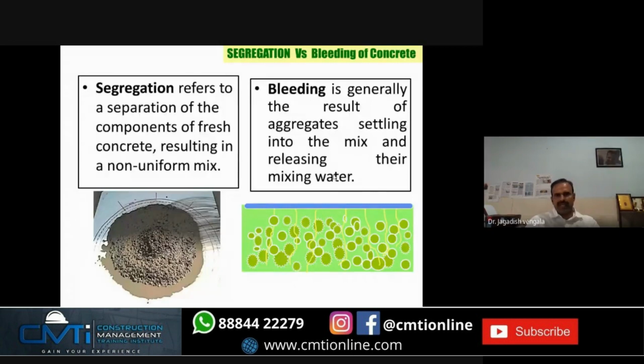So just to give you the difference between segregation and bleeding: segregation is separating out of all the constituents in the concrete, which results in a non-uniform mix. That means the water cannot be held by all the other constituents. Bleeding is generally a result of aggregate settlement, and the mixed water, that means cement water, releases the excess water. It forms on the top, or sometimes it bleeds out. So these are the problems you will get if you are just adding the water to achieve flowable concrete.